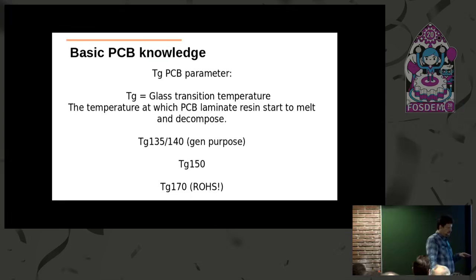Why? Because if you have a board with teeny holes, the plating inside the holes, when the PCB is heated in the reflow oven, starts to expand, and it cracks the plating inside the holes. And these micro cracks are very dangerous because when the PCB cools off, they might make connection again. So you put the PCB on test, everything is working, then it goes in the field and fails. And you start wondering what is wrong. In most cases, this is your PCB expanding during the reflow. But when it cools off, it makes a non-reliable connection, but still a connection, which might pass your functional testing. So if you want to make demanding electronics which work at high temperature, low temperature, always select TG 170.